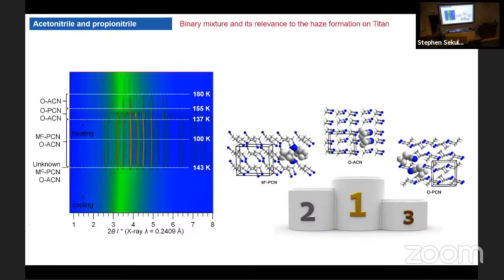The take-home message is, if we want to guess what kind of structures we will have on Titan when we have pure or mixed acetonitrile and propionitrile, it is an utter mess. We can make assumptions about what would be the most stable one. We can say, okay, the acetonitrile in the orthorhombic form might be the most stable one because that one has been quenched and it's stable, and in perpetuity should not transform to anything else because it's a thermodynamically stable form. But what would be the second most likely structure on Titan?